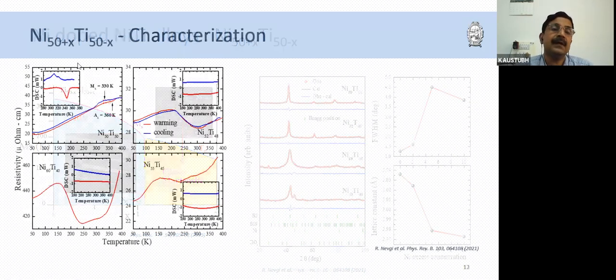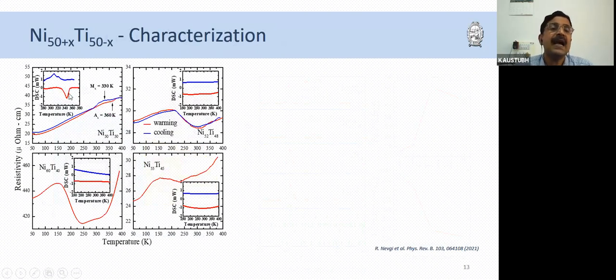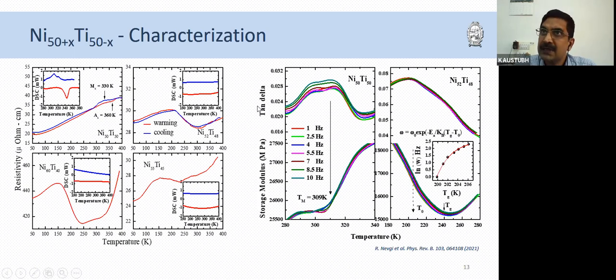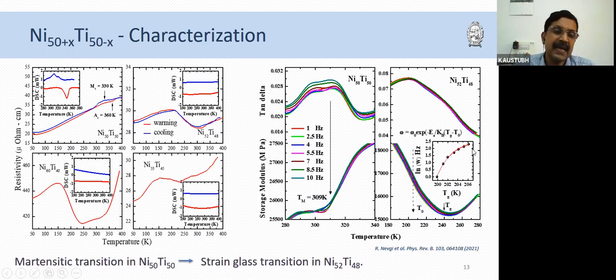So we looked at the DSC and resistivity, and in nickel 50, titanium 50, we could see the first order or martensitic transition very clearly, and that was absent in all the non-stoichiometric alloys. If I look at the frequency dependence of elastic modulus, then we can see the martensitic transition in the stoichiometric alloy, whereas you can see the frequency dependence of the T_g in the non-stoichiometric alloy, and it follows the Vogel-Fulcher relation. So what we could say is that we were successful in converting the martensitic transition in nickel 50, titanium 50 to a strain glass phase in nickel 52, titanium 48.